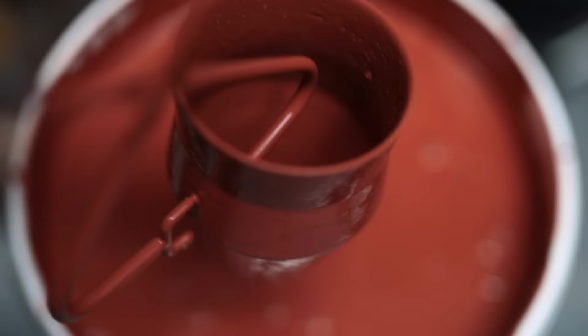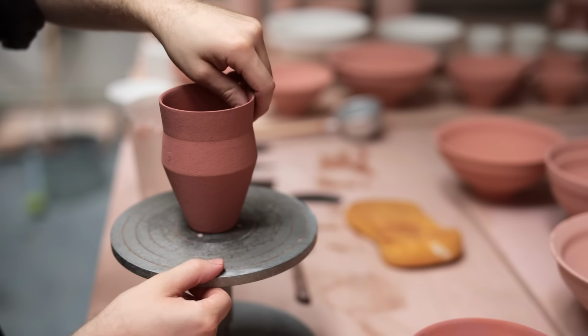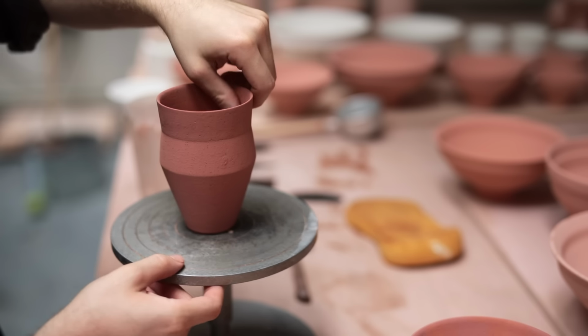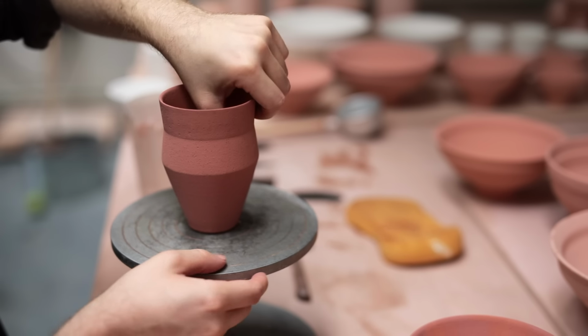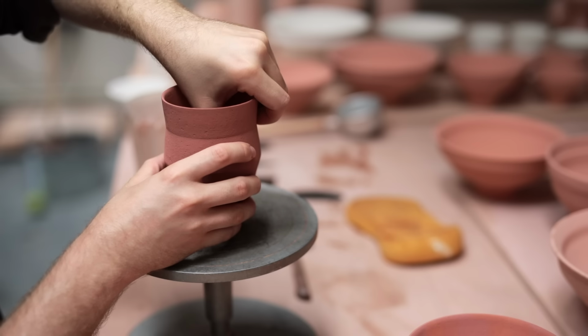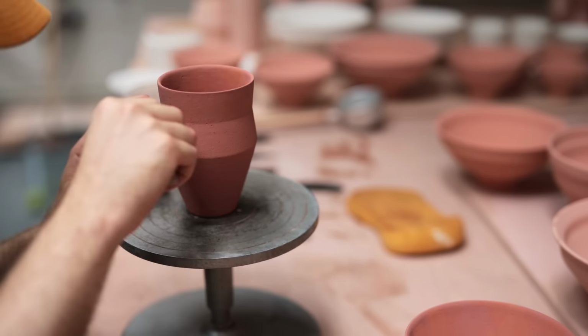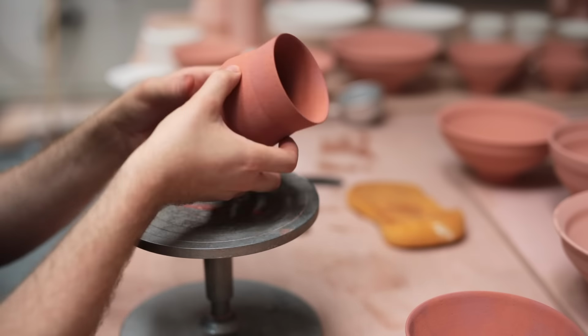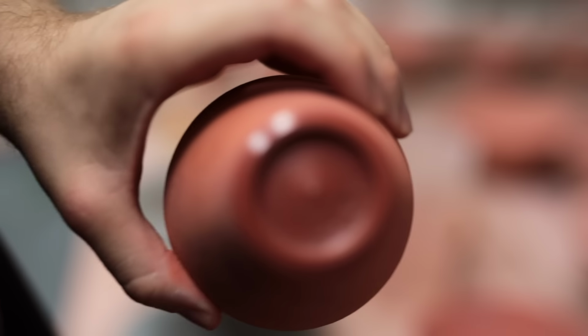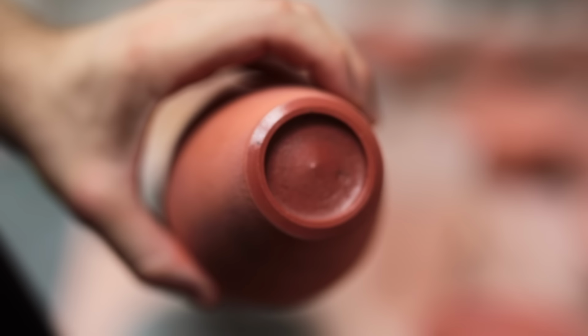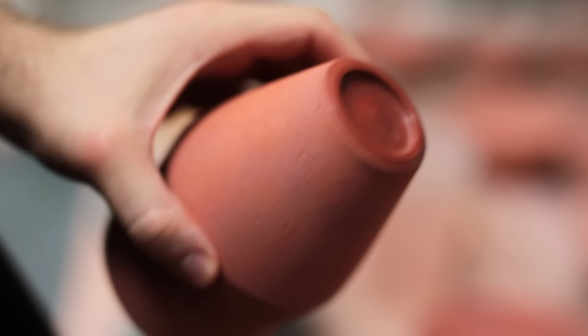The glazing still isn't quite finished though, as each pot now needs to be tidied up. I gently rub over the surface, especially where the tong marks are, and the glaze dust that's removed through the abrasion is enough to fill and hide the tong marks, as well as any other small inconsistencies in the surface. The last step is to sponge the base clean on each, so it looks something like this, after initially looking messy like this.